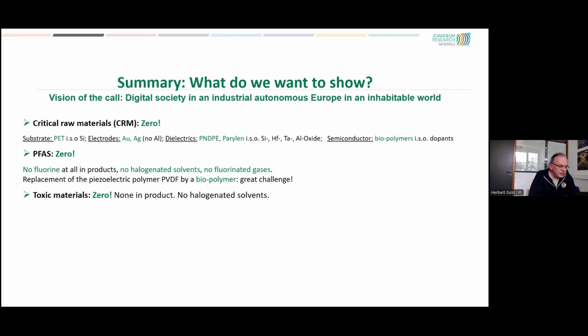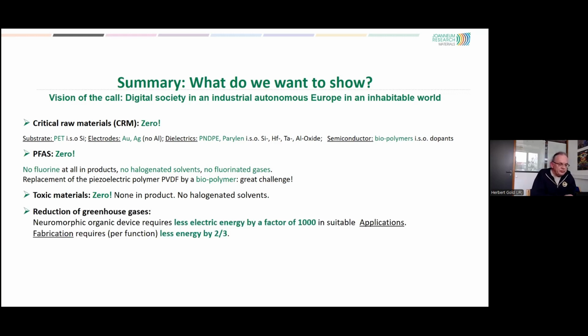And toxic materials in the product, we have 0, no halogenated solvents as mentioned. And the reduction of greenhouse gases is through the use of neuromorphic organic devices in suitable applications. This is a huge reduction. And in the fabrication was a difficult estimation. So we guessed that we would need less energy by 2/3, but as these per function, which is important there. So the very minute areas of the silicon electronics and the huge areas of the organic electronics make it quite difficult to compare, but still this was the best of our knowledge, our guess of energy saving in the fabrication.